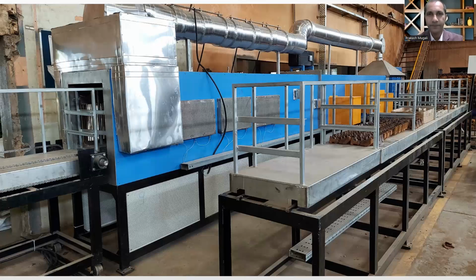Transparent. So as you say in your presentation, the principle of this particular drying is you are supplying these microwaves which go inside the core, the center of the core. It is absorbed by the moisture. Then it gets evaporated into vapor, and vaporization creates the heat. Once it becomes vapor, because of vapor pressure, it will come out of the core. And because of the hot air, it will be carried out of the oven. So your moisture goes down, which means your core is dry. Yes, so that is why it is dried inside also. That is what you like to say. That's right.